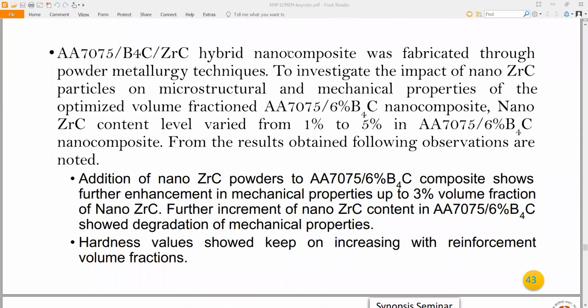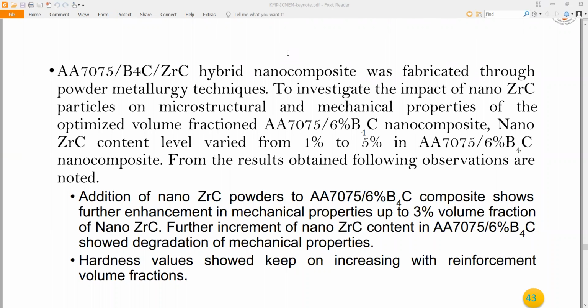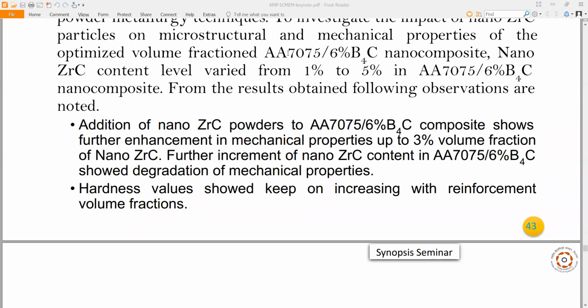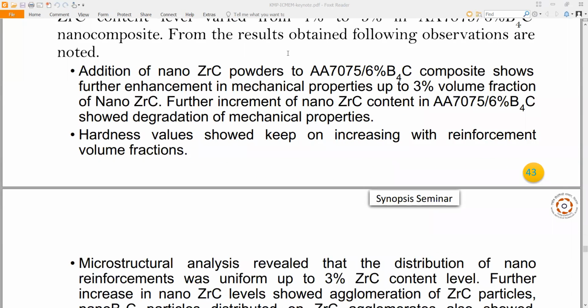Then AA7075 B4C ZrC hybrid nanocomposite was fabricated through powder metallurgy techniques to investigate the impact of nano ZrC particles on microstructural and mechanical properties of the optimized volume fraction. AA7075 6% B4C nanocomposite, nano ZrC content level varies from 1% to 5%. From the results obtained, the following observations were noted. With addition of nano ZrC powders to these composites, there is further enhancement in mechanical properties up to 3% volume fraction of nano ZrC. Further increment of nano ZrC content in AA7075 6% boron carbide showed degradation of mechanical properties. Hardness values kept on increasing with reinforcement volume fraction.